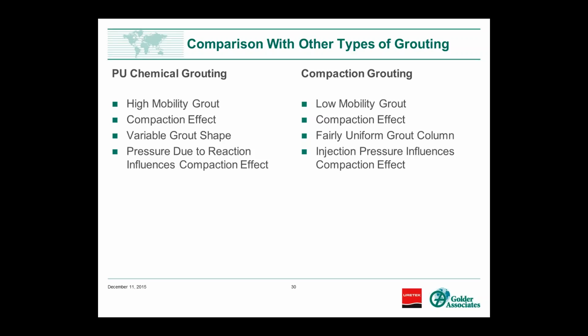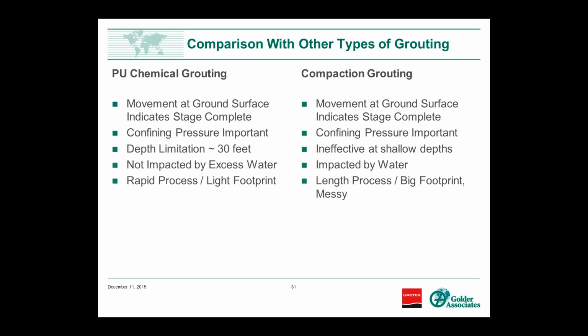And with the compaction grouting, the biggest difference I think is that the pressure you are injecting with at the surface, accounting for losses in the pipes and everything, that's the pressure that's doing the soil improvement at the injection point. Whereas with polyurethane, the pressure at the surface doesn't really mean a whole lot to you. It's really the pressure that's being achieved by the chemical reaction. That's what's causing the soil improvement. In both cases, watching for minute ground surface movements is one of the quality assurance methods, and in both cases you need the confining pressure so that the grout stays where it's supposed to be working.